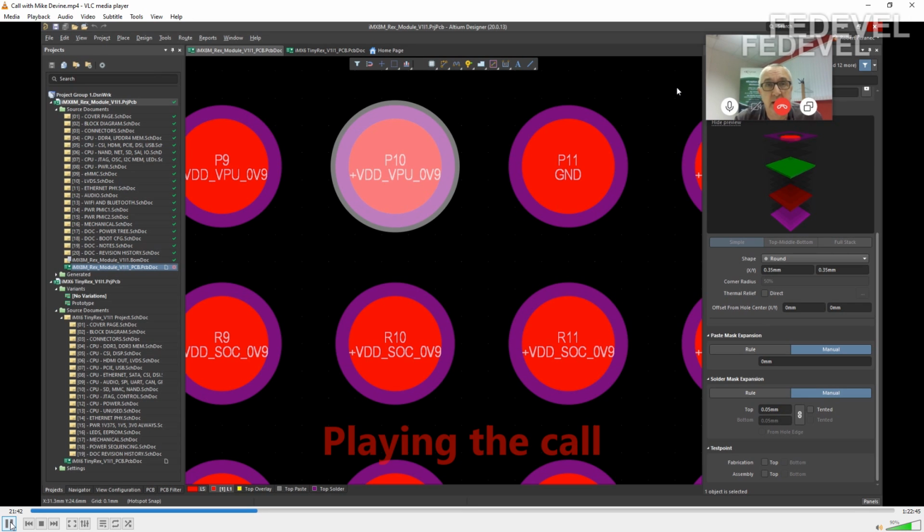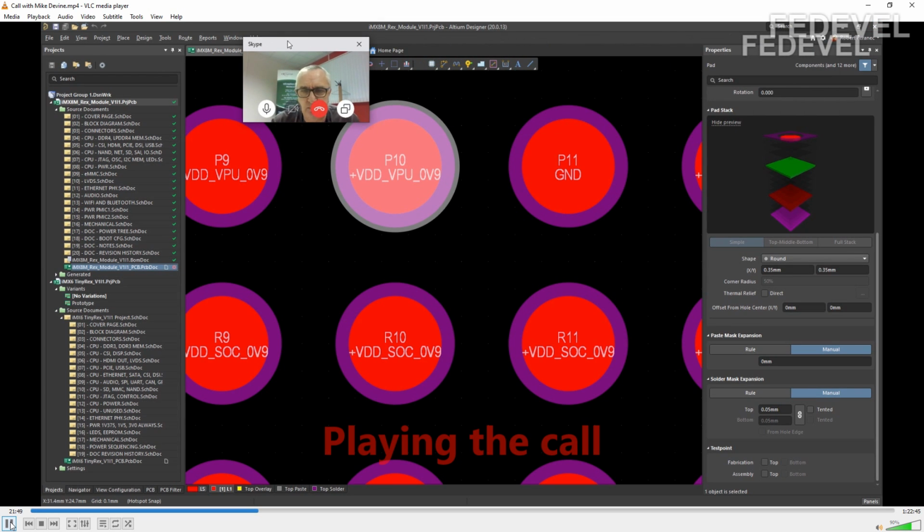And also, in some instances, because we manufacture boards that are using 0.2 pitch BGAs, and the only way they can fan out is to go to a towered microvia. And again, towered microvias, we manufacture a considerable amount here on a daily basis, but that is always going to be the risk when the board receives any high thermal shock.